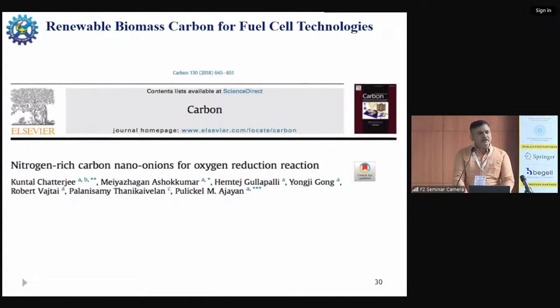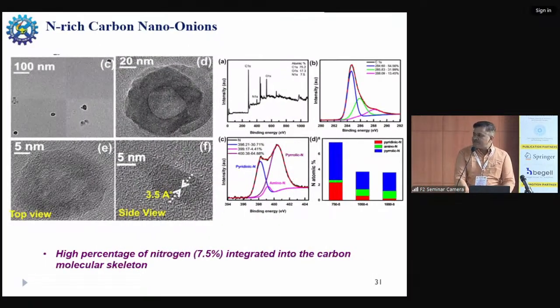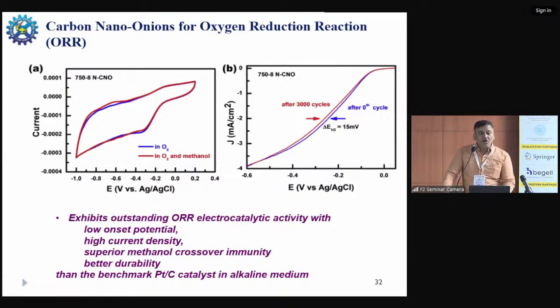And in this example, we tried to do the same reaction at a specific temperature, say 750 degrees Celsius for about 7 to 8 hours, and we found that we are able to incorporate more nitrogen, close to about 7.5%, and we are able to form very nice onion structures. And we tried to use this for the oxygen reduction reaction, and we observed that this exhibits outstanding ORR electrocatalytic activity with good properties like high current density, superior methanol crossover immunity and better durability compared to the benchmark platinum carbon catalyst.